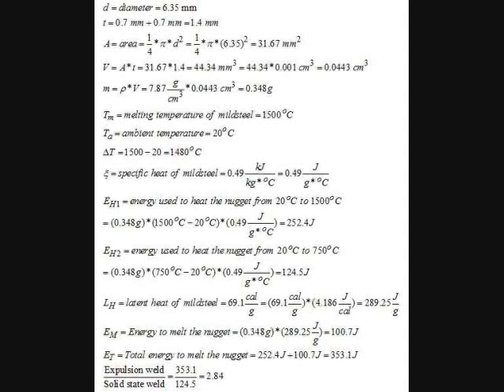Let's say the melting temperature of mild steel is 1500 C, ambient temperature 20 degrees C, so we have to raise this through 1480 degrees C. And the specific heat of mild steel is 0.49 joules per gram per degree C. So we calculate that to raise this little cylinder 1480 degrees C, it takes 252.4 joules.